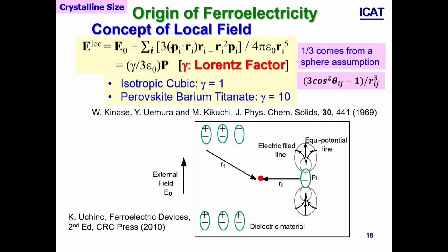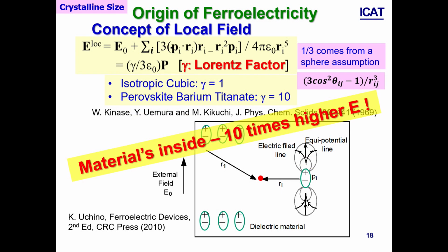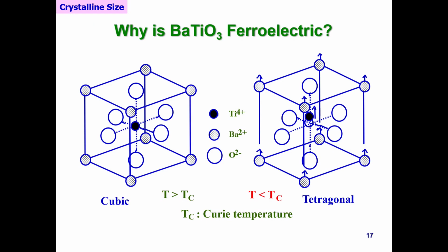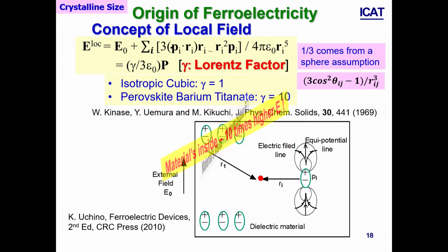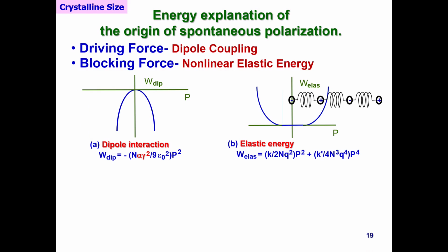In that case, applying electric field E, usually dipole moment related electric field is small, but in really highly dense materials, actually this is enhanced. So the field inside the material is 10 times higher than the external electric field, such as the barium titanate case. This gamma is a Lorentz factor, isotropic materials is 1, but in the perovskite particular structures, this becomes 10, okay? Very high. So according to this large internal local field, a dipole interaction comes out.